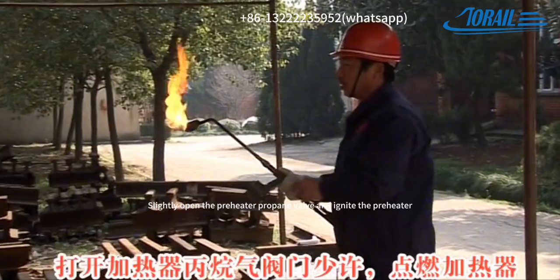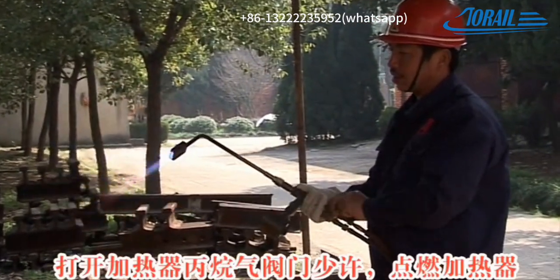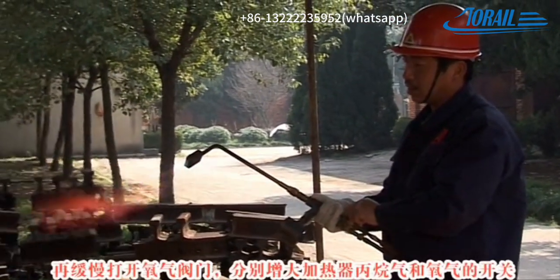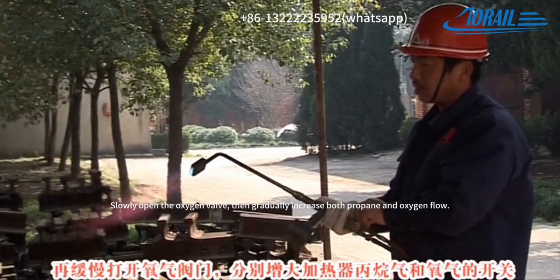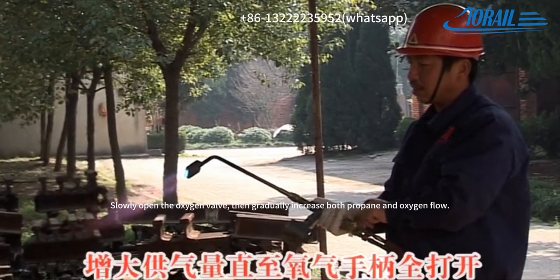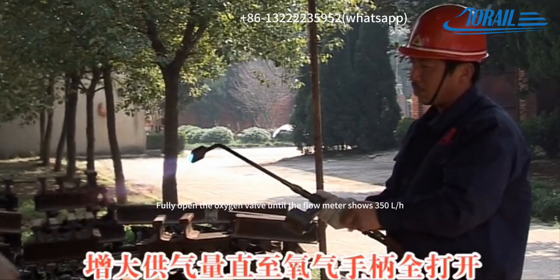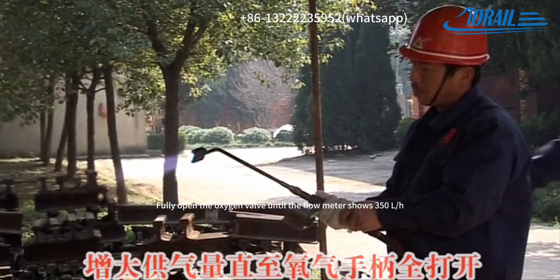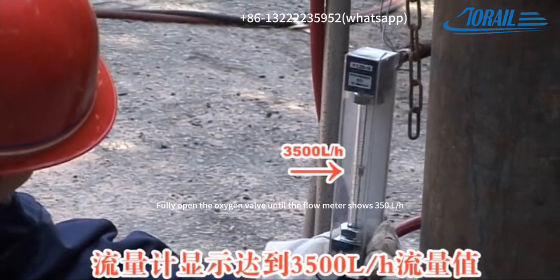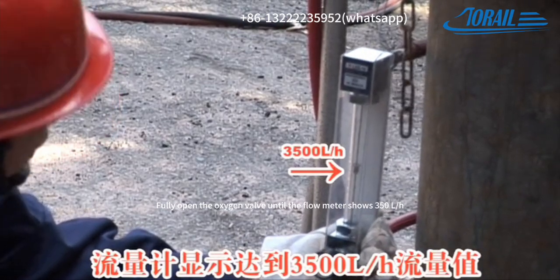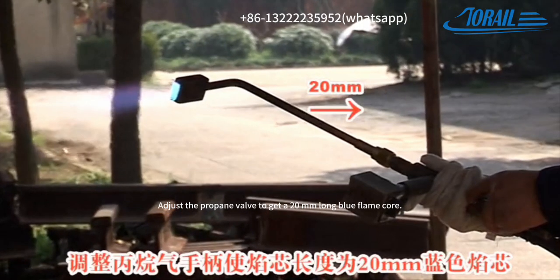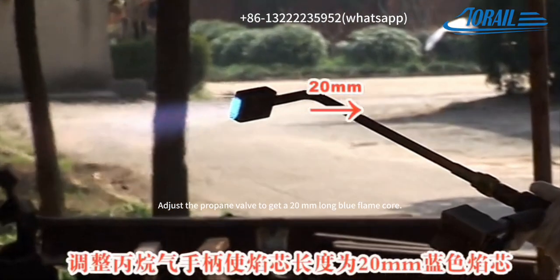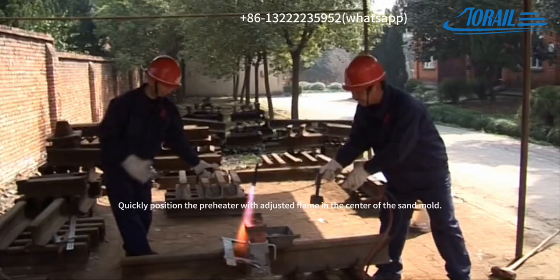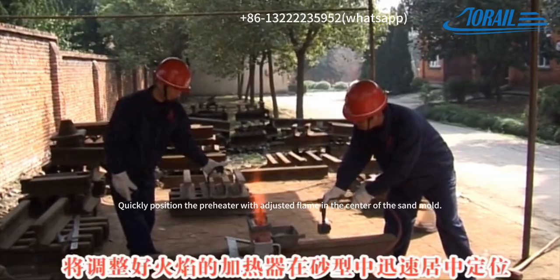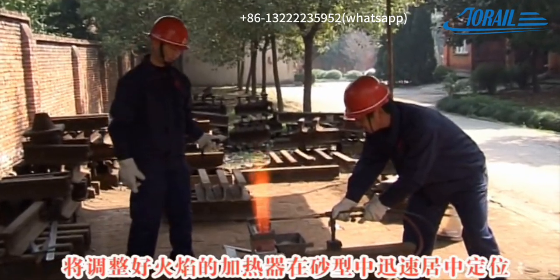Slightly open the preheater propane valve and ignite the preheater. Slowly open the oxygen valve, then gradually increase both propane and oxygen flow. Fully open the oxygen valve until the flow meter shows 3500 liters per hour. Adjust the propane valve to get a 20 millimeters long blue flame core. Quickly position the preheater with adjusted flame in the center of the sand mold.